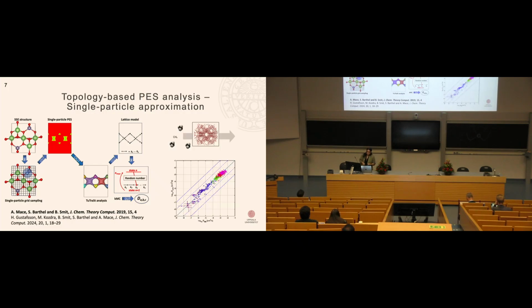Okay, so this method was first developed for studying methane diffusion in zeolites. And for the inert methane gas molecule, this single particle model is a very good approximation, and we can use inexpensive force fields to compute accurate diffusion coefficients for methane in nanoporous materials in only minutes on a desktop computer. And what we have here is the comparison of our approach versus atomistic level molecular dynamics simulation, for different nanoporous materials at different temperatures, and we get a quite accurate prediction at a very low computational cost.